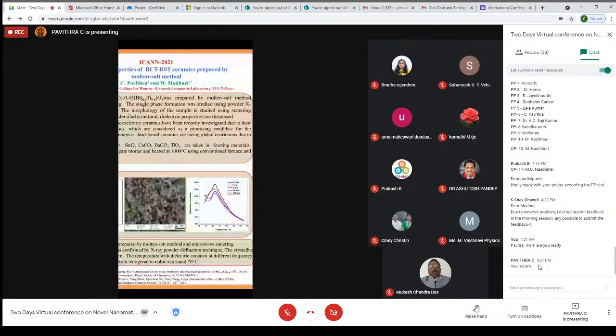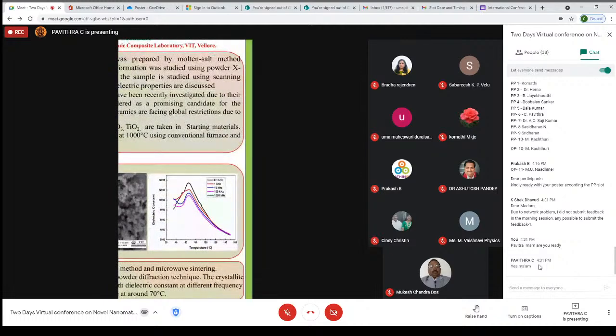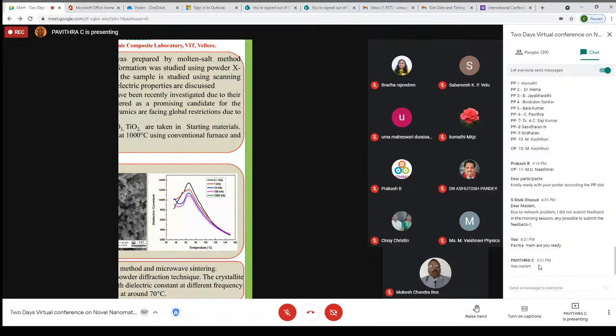The XRD clearly shows a cubic crystal structure, and single phase formation in the prepared sample. From the SEM images I have measured the particle size of the prepared sample. It's around 47 to 50 nanometer. The dielectric constant I have measured versus temperature. I increased the temperature from room temperature to around 150 degrees centigrade, at various frequencies, for example 0.1, 1, 10, 100, 1000 kilohertz, and I have plotted it here.